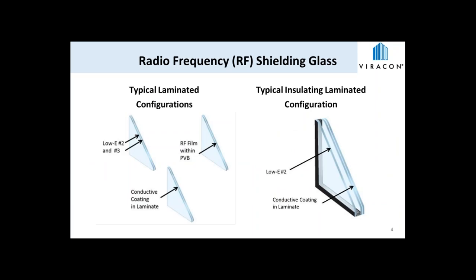So typical RF shielding glass can consist of several different configurations. There are three common laminated makeups and one common insulated laminated makeup. The laminates on the left-hand side can include one of three makeups: a double low-E laminate with the number 2 and number 3 coating layers inside the laminate, an RF film laminate, which includes an RF blocking film layer that is placed up against the surface of the PVB, or a conductive coated laminate, which includes a transparent conductive oxide coating either on the interior of the laminate, within the laminate, or ideally on both surfaces.